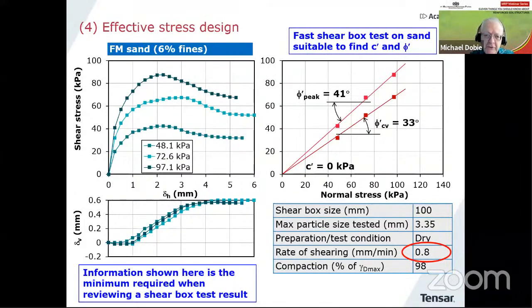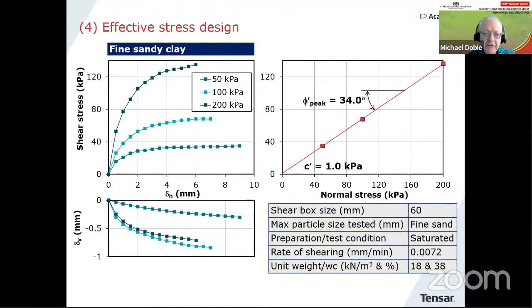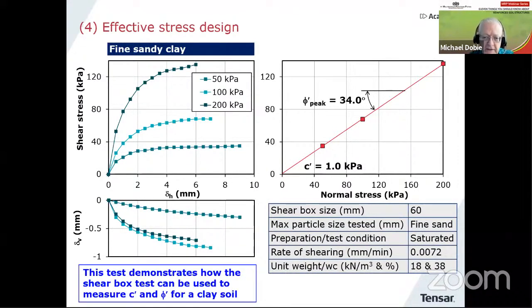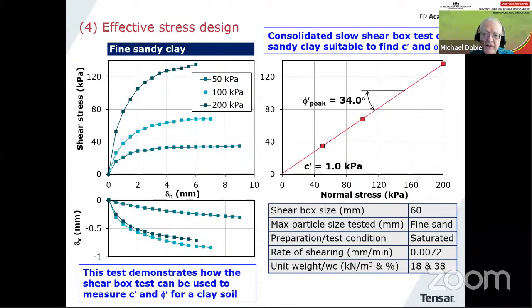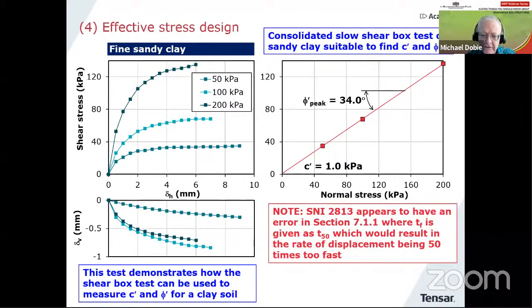If I now switch this picture to a fine soil, so this is a similar test on a fine sandy clay, also a picture we looked at back in one of those early webinars, then we can get very nice results in terms of effective stress, in other words, C dash and phi dash for a fine soil, but the test has to be a consolidated slow shear box test. So if we now look in the tabulation down below, we see a rate of shearing of just 0.0072 millimeters per minute. So it's very, very slow. So if you want to get suitable results from this kind of testing in terms of effective stress, then you need to test slowly. I made this point also back in the second webinar that the Indonesian standard which covers this test method appears to have a slight error in the way you calculate the rate of shearing. Basically, it's 50 times too fast.